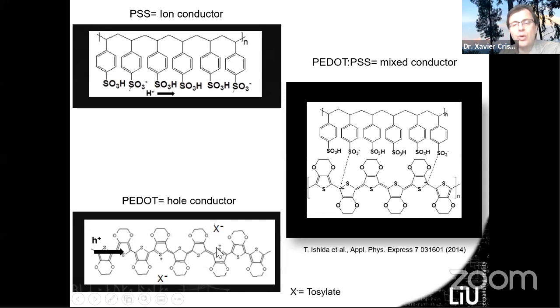Now it's possible also to combine those materials. So for instance, instead of using those X- that are small anions, you can actually use these sulfonate groups from the other polymer. And then you can merge them together in a blend or composite of polymer, which in that case is PEDOT:PSS. Then you end up with a material that is quite interesting because it conducts at the same time the protons or cations, as well as electronic charge carriers in the form of holes mostly. So you have three types of polymer: the ionic conductors, the electronic conductors, and then the mixed conductors conducting both ions and electrons.